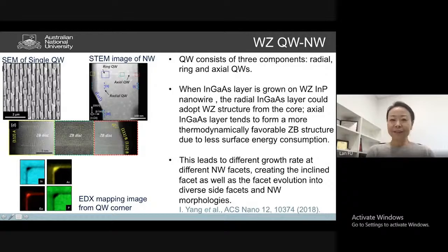It's very easy to say, just by switching for a few seconds, you grow one thin layer of indium gallium arsenide. What you see is this change of morphology. I still hope you remember that beautiful hexagonal shaped indium phosphide nanowire array I showed you a few slides ago. And then this SEM picture shows that when we put in just a few seconds of InGaAs growth, the morphology of the nanowire becomes like that. And if you look at the cross-section view of the TEM, you can actually see this thin layer of indium gallium arsenide quantum well formed inside the nanowire.